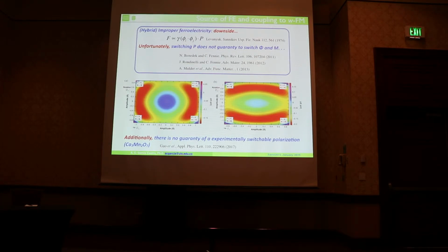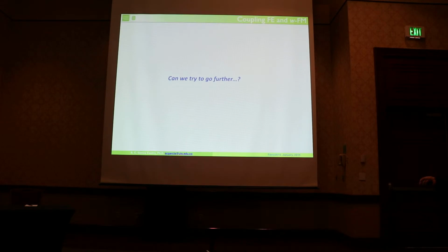So it was claimed that through strain you can reach this energy landscape. However, it depends on strain and on other conditions, so the balance between the energies and between the phonons is really smooth. Additionally, there is no guarantee of experimentally switchable polarization in this material, which was the prototype, at least at room temperature. So our idea was, can we go further? The answer is yes, or we can try.